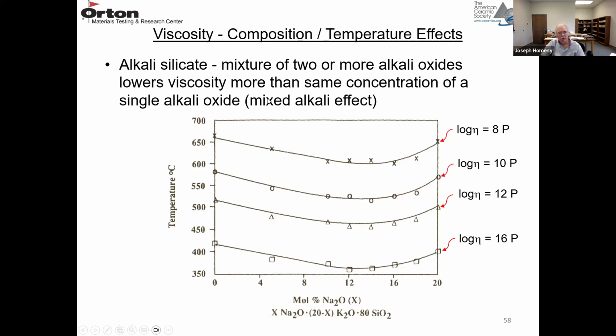There's something known as the mixed alkali effect. So if you have a mixture of two or more alkali oxides, that lowers the viscosity more than the same concentration of a single alkali oxide. So temperature versus mole percent Na2O is X. So if X is 20, you're at 20 mole percent Na2O. If X is 0, you're at 20% K2O.